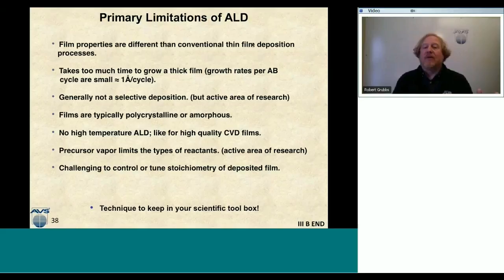Films are typically polycrystalline or amorphous, as I've mentioned previously. There's no high temperature ALD like there is for these high quality CVD films. So with CVD, I can make that film, I can have that substrate very, very hot. But in ALD, there's an upper limit to the temperature at which I can run the ALD chemistry. And that will limit its properties and make them different than what we might see in a CVD film. Precursor vapor pressures limit the type of reactants.